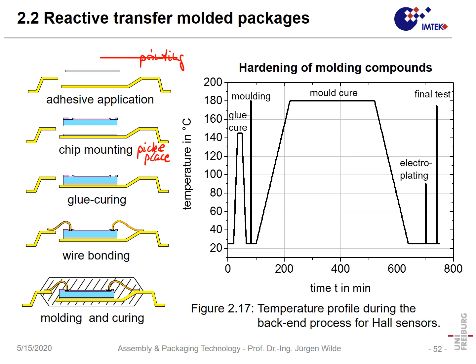After the hardening, the lead frames are transferred to the wire bonding machine, and here the individual wire bonds are created on an automatic wire bonding machine. A typical diameter of the wire bonding is 25 micrometer, and in our case here we use gold as a material. After the wire bonding, we go into the molding process, which we will see in more detail.